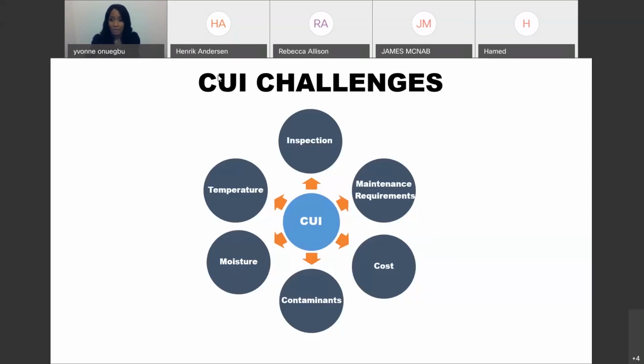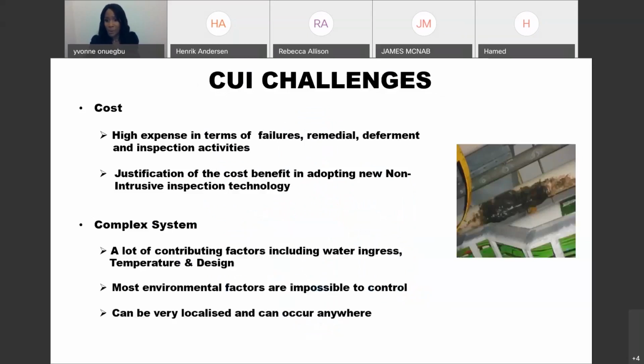So what happened? Basically, water can move underneath insulation and be collected by associated pipeworks and be deposited elsewhere, in this case in this enclosed module. We also have issues with detection. The external appearance of the cladding may not correspond to the condition of the underlying pipework. So in some cases, we might not even know we have CUI until the insulation is removed, or until corrosion gets to a stage where a failure occurs and we get a leak.